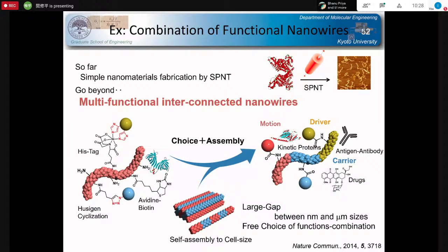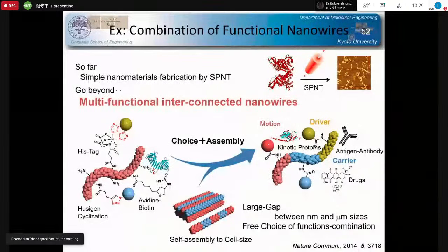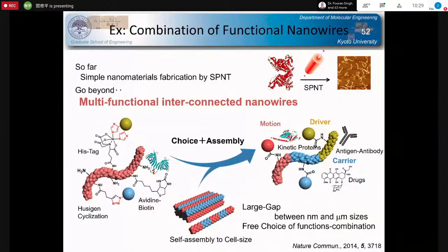As you suggested, the deposited energy density in the core area was extremely high, and we speculate that the chemical structure inside of the nanowires is no longer maintained, and molecules themselves are completely damaged at the core areas. This reminds us that after the isolation of the nanowires, with successive chemical treatment, we can dissolve only the core part, eventually leading to tube structures. And now we are trying to realize such one-dimensional materials.